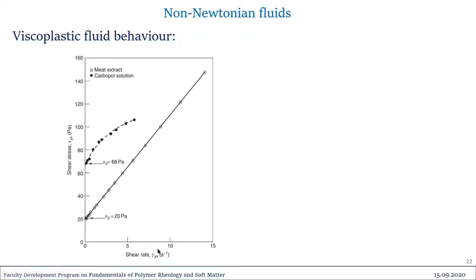This is shear rate. It is nothing but the rate of deformation. Fine. So here it will start flowing, and once it starts flowing, you are able to connect all this data with a straight line. On the other hand, when you are talking about this Carbopol solution, it is only able to flow once it exceeds the stress value of 68 Pascal, but it is not linearly behaving. It will give you non-linear behavior.